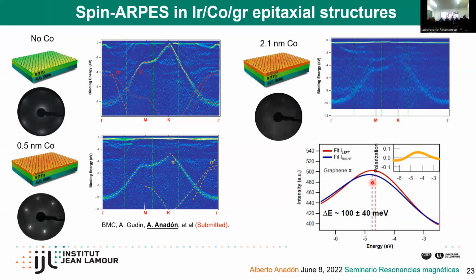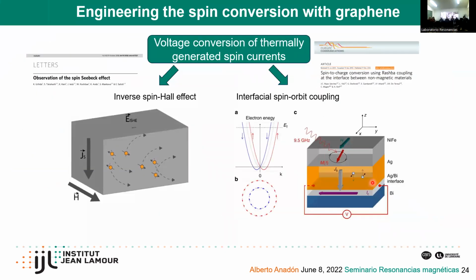Okay, so now let's take advantage of all the physics that we have obtained from our graphene samples. As you know, I discussed this before, we can use the inverse spin Hall effect, for example, in platinum to generate spin currents or charge currents, or convert one to the other. So we can do this also in interfaces, as I just said. So let's take advantage of the graphene cobalt interface to do a spin conversion.